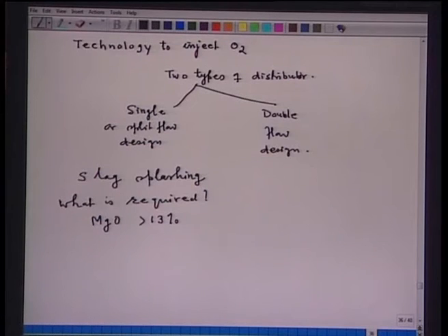At the same time, FeO content of the slag should be approximately 20%, because FeO will form a low melting point phase, as well as a good adhesion between the slag and refractory. MgO forms a high melting phase. So, if both are combined together, then a very good coating of the slag results on splashing.